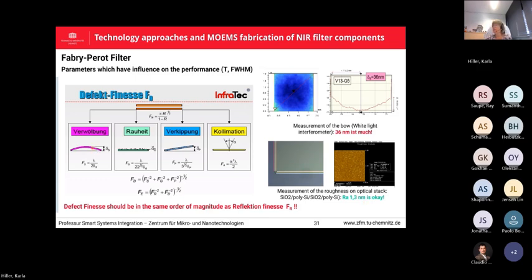But this bow here also looks very small, like 36 nanometer over a 2 millimeter area, but we found this is already an influence which will give us a certain deviation from the ideal case. So we should keep this as small as possible. This means we have to handle the stress of the layer deposition accordingly. And finally we found out that the so-called defect finesse should be in the same order as the reflection finesse, which is mainly defined by the reflectivity of the optical layer stack. So it does not make sense if this is very good and this is not so good coming from these influences, because then the total effective finesse of the filter will be limited by the largest contribution of the failures.